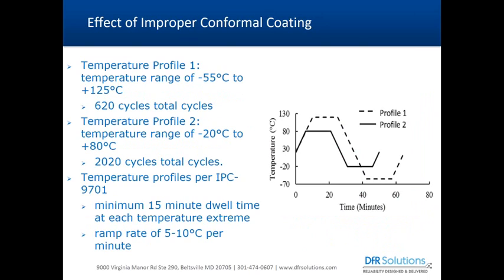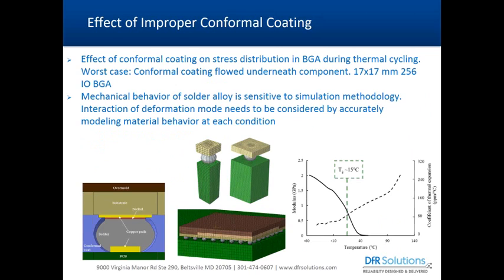We tested two temperature cycles: a standardized IPC minus 55 to 125°C cycle, and a less aggressive minus 20 to 80°C cycle to examine temperature profile dependence. We initially approached this study numerically by modeling the mechanical behavior of solder joints due to thick coating application. We will show the results for thick conformal coating. At the end we show experimental results — there was no meaningful difference between standard coating and control components, so no adverse effects from acrylic spray coating as long as it doesn't wick underneath the package.